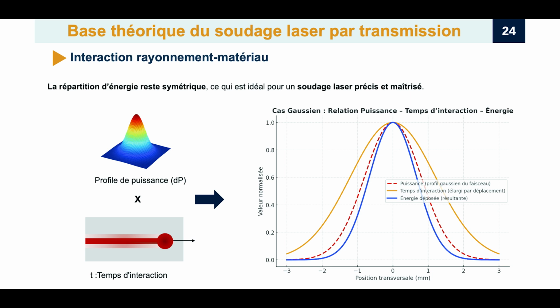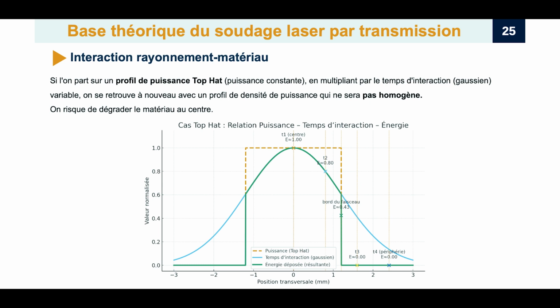Okay, so the engineer thinks, right, the Gaussian power profile is the problem. I need uniform power. So they switch to the engineered top hat beam. P is now uniform. Surely that fixes it. And this is where the subtle physics of motion really trips up that initial logical engineering step. Yes, you now have a uniform power, P, across the beam spot thanks to your top hat profile. But the laser is still moving, which means the interaction time, T, is still Gaussian, still peaked in the center of the track. So even with flat P, when you calculate E equals P times T, because T is Gaussian, the total deposited energy, E, is still highest in the center and tapers off towards the edges. It follows the shape of the time profile. So the top hat is better than the Gaussian, maybe, but it doesn't solve the fundamental problem. Exactly. The top hat profile is an improvement.